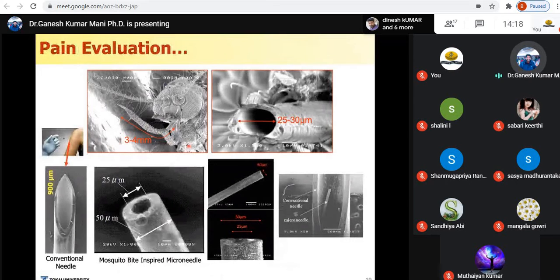So here you can see the mosquito's labium is 25 to 30 micrometer, and this is a titanium microneedle that we made in our laboratory using the sputtering technique. For the sputtering, we take a copper wire with the same diameter as the mosquito's labium, say 25 micrometer, and then we coat it with titanium through sputtering. We have some customized equipment to perform this.